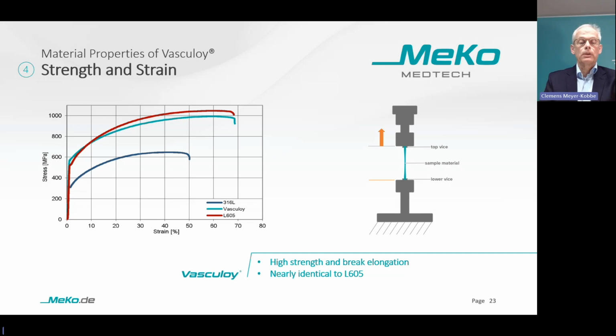With a higher nitrogen content, we would be able to achieve much higher strengths for Vasculoy, but then we are losing the plasticity. That means a high break elongation. So the take-home message for this slide is Vasculoy has a high strength and break elongation nearly identical to L605, which is the standard material for coronary stents.